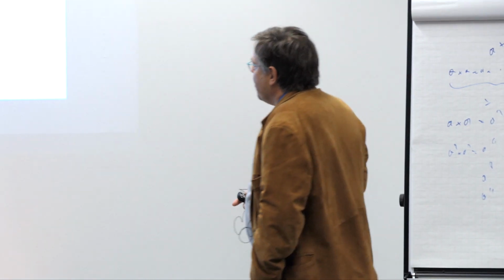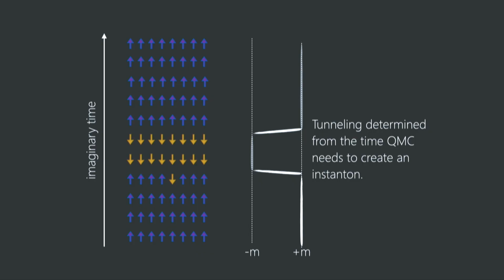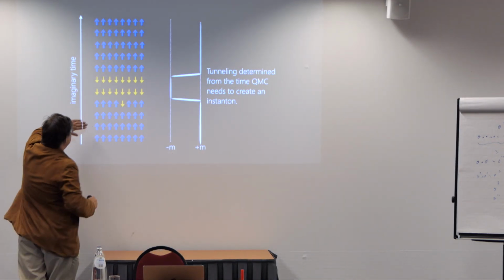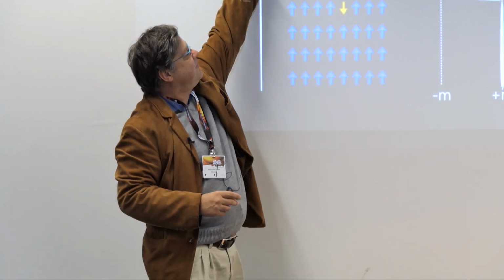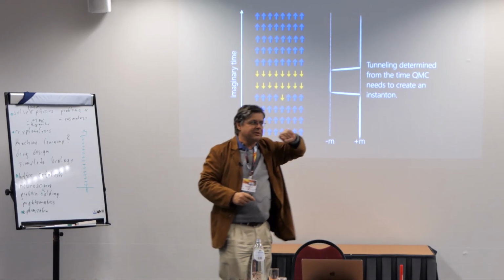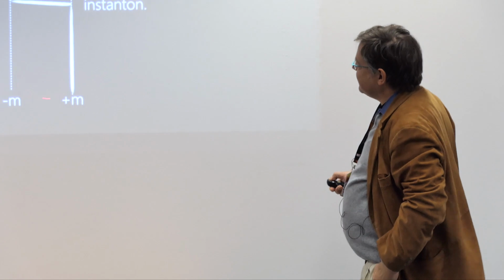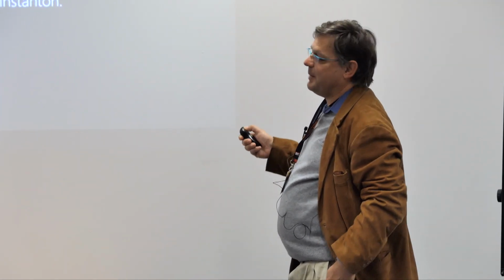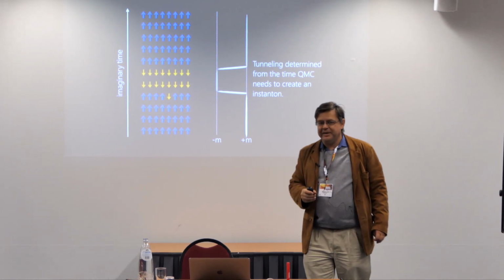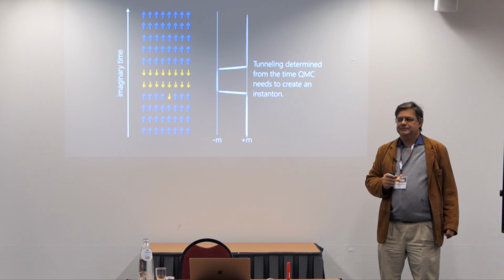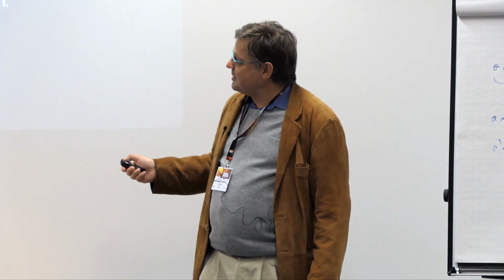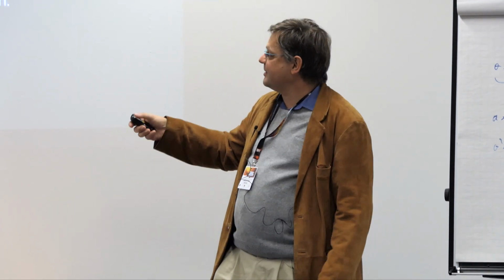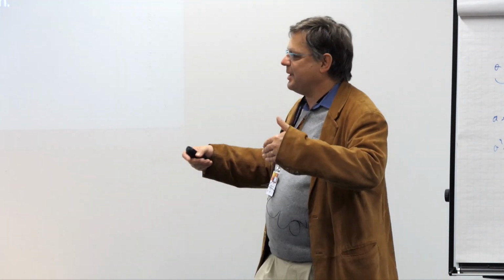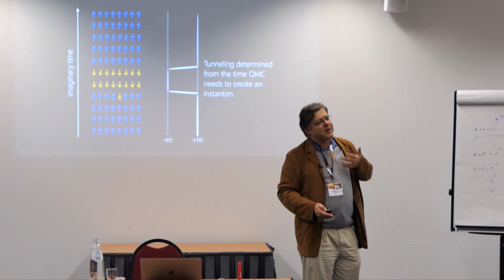What does it take in the path integral Monte Carlo simulation? In that simulation, I start out with all spins up. And then at some point, I get 2 instantons. I get one kink where suddenly the spins flip to all down, and then they again flip back to all up. So if I plot the total magnetization, it starts at plus, it jumps to minus for a short time, and it jumps back. And what is the cost of that? I have to tunnel through once and I have to tunnel back. The matrix element to tunnel is the gap, and that's again the gap. So the probability for that to happen is the gap squared. The time until I get there is 1 over the gap squared.